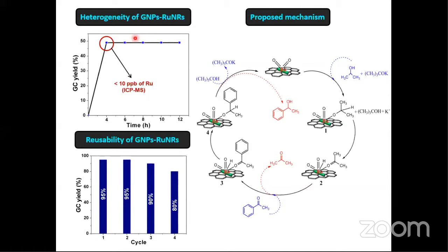There was no leaching. But when we analyzed the solution after the separation of the catalyst by ICP, the solution contains a very, very small amount of ruthenium. It means that there is a very insignificant leaching, but that was not sufficient to catalyze in solution state, right? So here you see that there is a slight reduction in the yield when you use the catalyst at the 4th run, but this can be increased by the calcination of the catalyst. This is without any process. If you employ it as such, there's a slight reduction because of the adsorption of some other reactant and solvent molecules on the solid support, right?